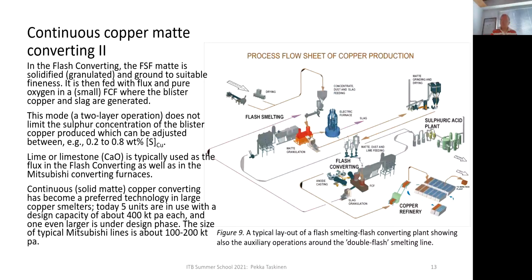What is nowadays more preferred, for one reason or another, I don't know, is the technology called flash converting. So in flash converting, we are using solidified and ground flash furnace matte, which is cold material, can be stored at site in big heaps, and when that is ground to suitable fineness and fed in flash melting furnace with pure oxygen, it can be oxidized directly to blister copper and slag.